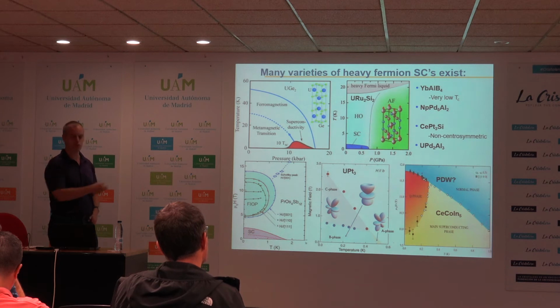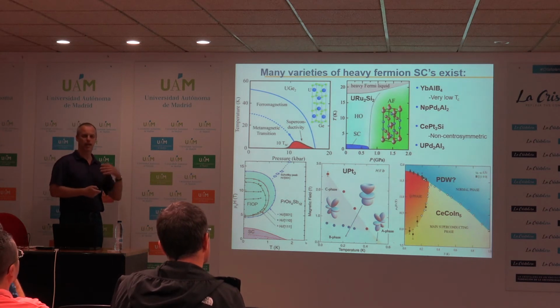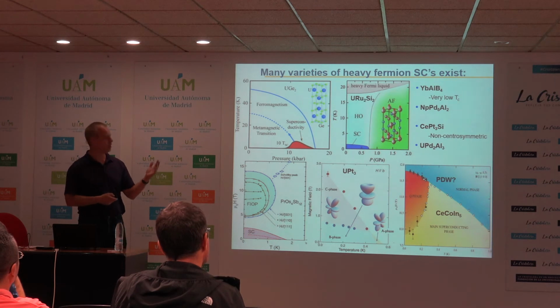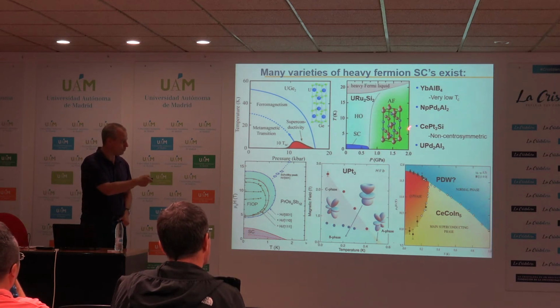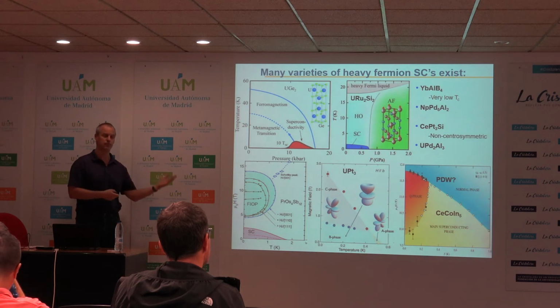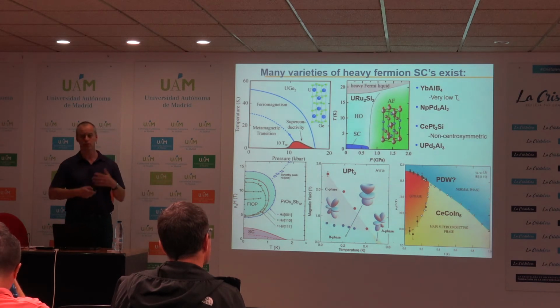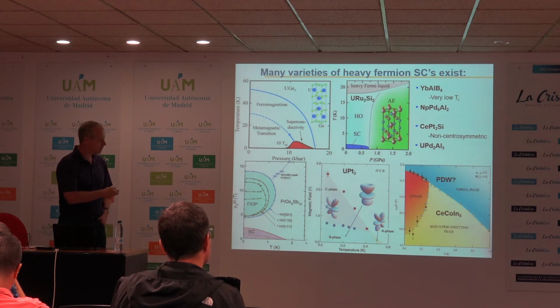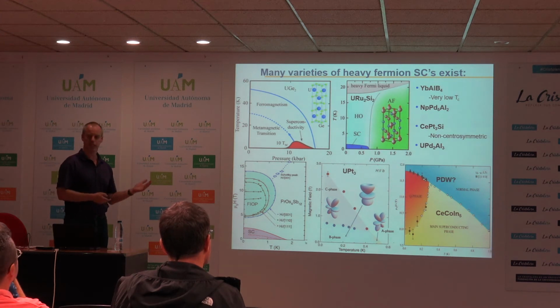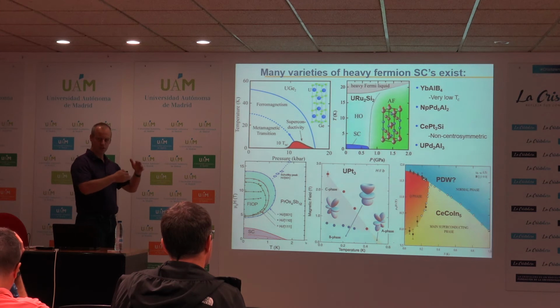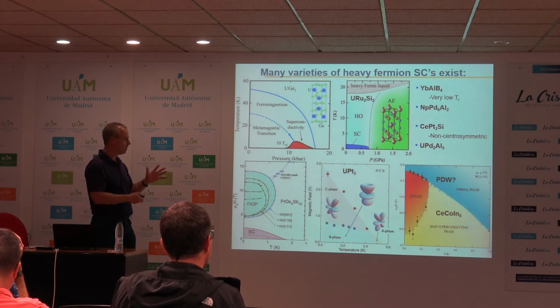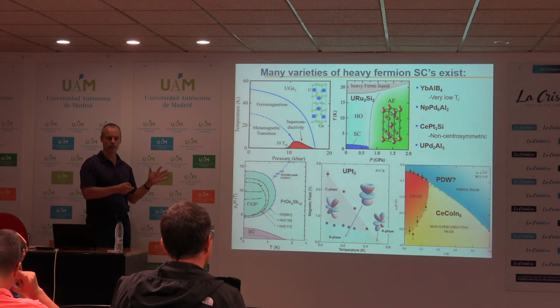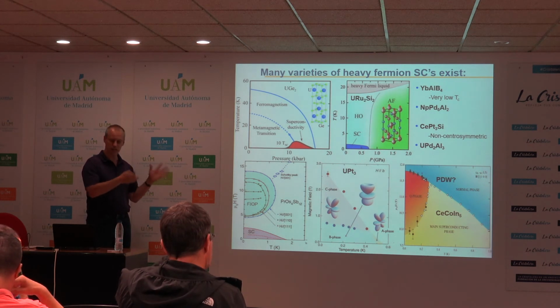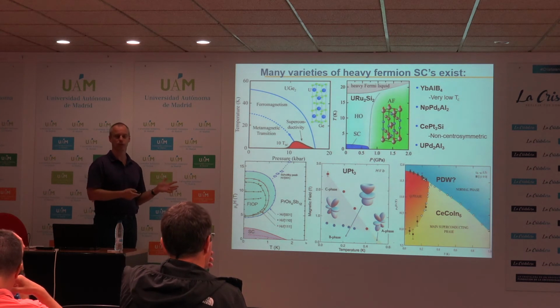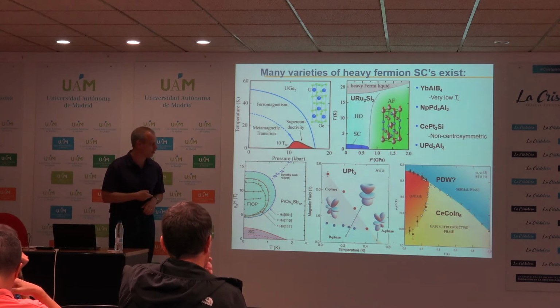There's a neptunium superconductor with a very strong Ising-like magnetic susceptibility in the normal state. Cerium platinum 3 silicon is non-centrosymmetric, so mixing of spin singlet and spin triplet components, because you break inversion symmetry, is present in the cerium compound. Uranium palladium 2 aluminum 3 orders antiferromagnetically before you get superconductivity. So there's a variety of different compounds again, and you can get lost in all the details. But I think just in general, it provides a rich environment for studying the different things that can occur.